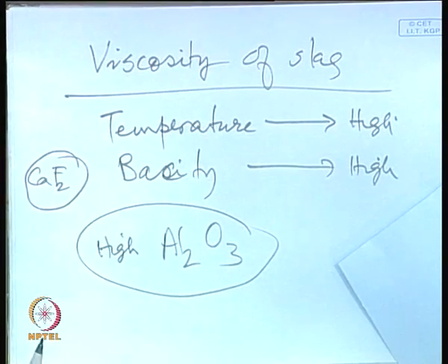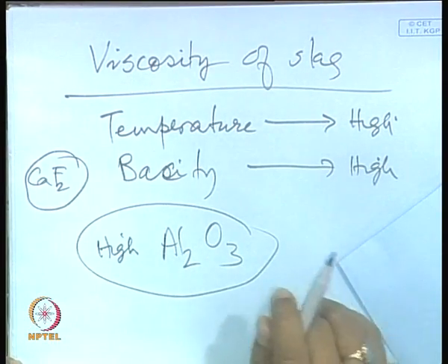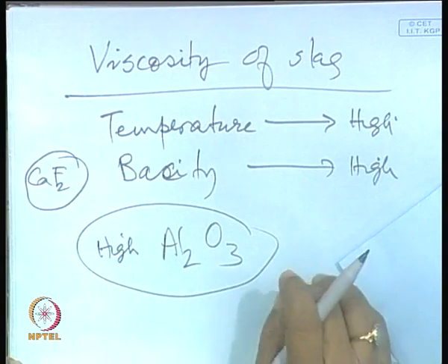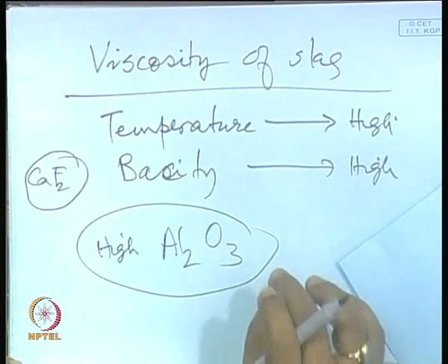Indian ores are very good, but alumina comes from ore as well as some from coke, and Indian slags used to be very highly viscous because of Al2O3 content. Many efforts have been made to remove Al2O3 from iron ore, but it is very difficult. So, you end up with slag with a lot of alumina, high viscosity. Many efforts were made to find out how to bring down this Al2O3 content. You cannot simply go on adding a lot of calcium oxide to increase the basicity,